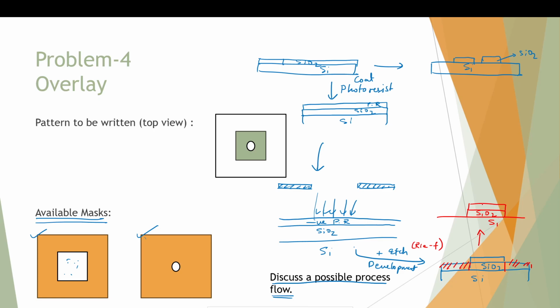For this we have studied how we can remove photoresist, right? Different cleaning methods are there, and they work even for the photoresist. So we can do an acetone IPA clean, followed by a piranha clean. Or there are special PR removers also available that we can use to get rid of this photoresist layer. Then finally we will just have silicon and SiO2. Okay, so far so good.